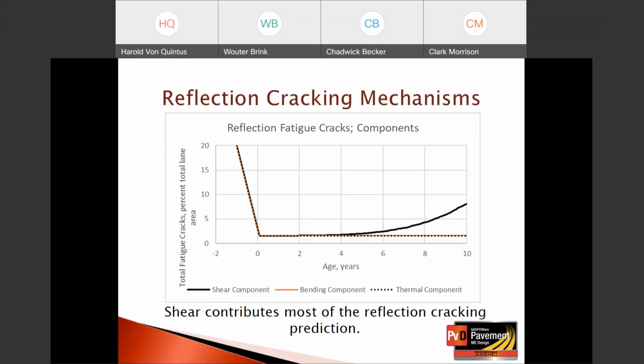The bending is the solid orange line at the bottom, and the thermal component is the dashed black line at the bottom. They do provide some contribution, but it's minor compared to the contribution of shear. So shear contributes most of the fatigue reflection cracking prediction in most cases, or in the majority of the cases.